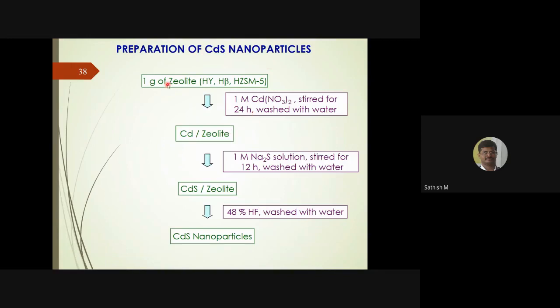A few years before, we made cadmium sulfide in a confined environment, like in the zeolite matrix. We collected different zeolites. Zeolites, you know, are a porous structure. In between, we put some cadmium ion by stirring with some cadmium nitrate solution, and then you can make the precipitate of cadmium sulfide. Since cadmium sulfide is an ionic compound, you could put 48% HF, and only the silica matrix will come out.